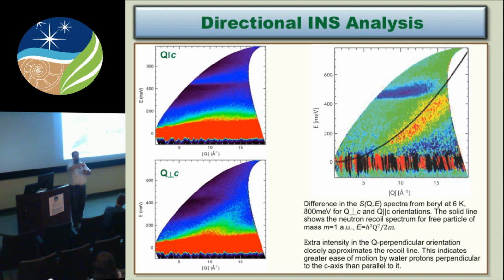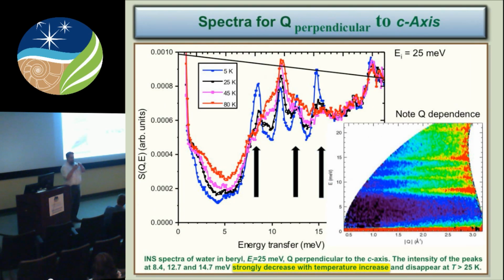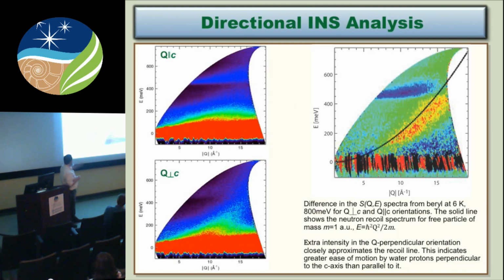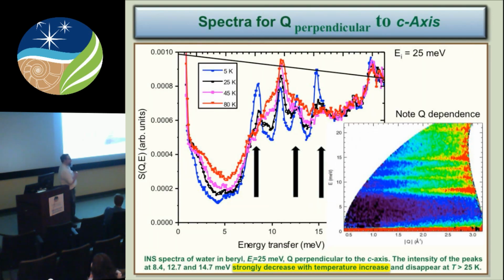So what that's telling you is about the motion of water perpendicular to the C-axis. You remember you've got this tube, but it turns out water motions are easier, they're softer, across the channel than they are along it. Right? It's much easier for water to move this way than to move along the channel, in part because water molecules are stacked one above another, so they're hindering each other. You also see that there's a significant difference up here in that hydroxyl stretch. We'll take a look at that in a minute. Primarily that's orientational. It has to do with differences in the orientation of the Debye-Waller factors for the water motions within the sample. Again, because you have more vibrations across the channel than you have along it.